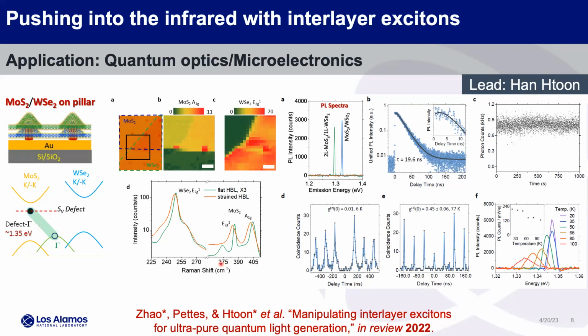The new thing that we found, and this is some Raman showing the strain. This is a strain mapping that I do with my system. So you can see we're diffraction limited. Peaks line up exactly where you put them. This is where the layers overlap with two of the 200 nanometer diameter pillars. Everything matches up perfectly where we expect it to. Strain, I think it was about 0.27%, and it's tensile strain. When we're on top of it, you go to a lower phonon energy.